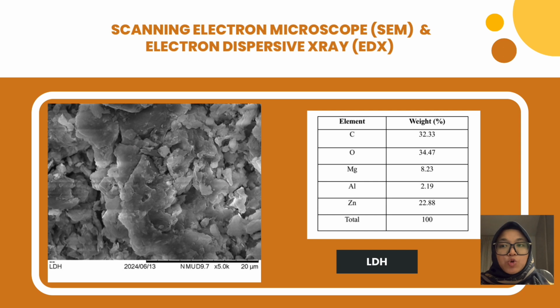Next, let us first look at the SEM EDX analysis for the LDH composite. The SEM image shows a flake-like morphology which indicates a high surface area that is beneficial for absorption. EDX analysis confirms the presence of essential elements with the following composition: carbon 32.33%, oxygen 34.47%, magnesium 8.23%, aluminium 2.19% and zinc 22.88%. These structural features contribute to the composite's effectiveness in absorbing the heavy metals.